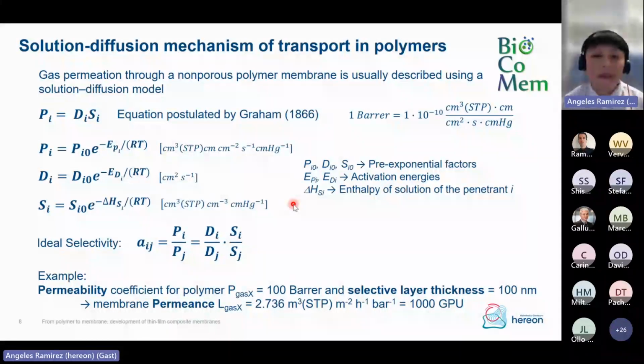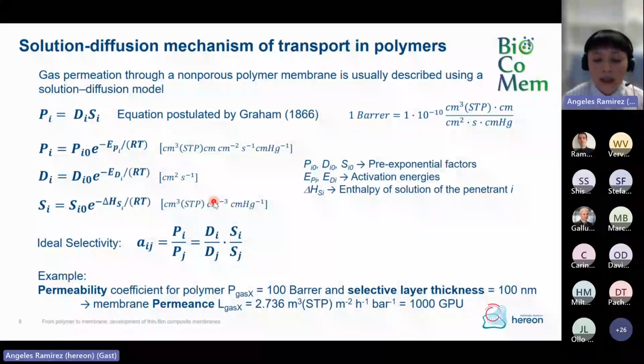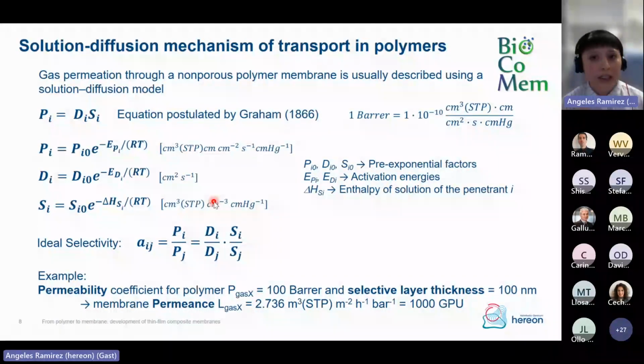So in the case of gas separations, this is the differences in pressure. Now, the diffusivity designates the kinetic factor, which indicates the probability of a gas molecule to move across these transient free volume elements within a polymer. And this will be mostly determined by the size of the gas molecule. Now, the solubility is a thermodynamic factor, and this will indicate the amount of gas that can be dissolved within the polymer under equilibrium, and this will be determined by the affinity of the gas towards a certain polymer matrix.